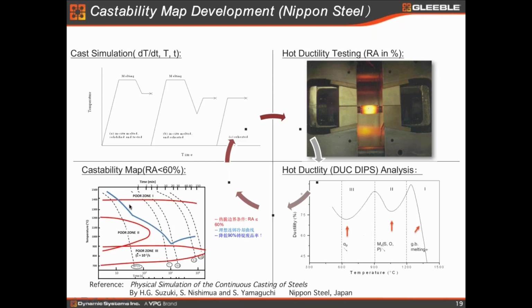So in this castability map you will see temperature versus time. They plot these three low ductility regions as contours in this map. We call it a castability map. What they see is this: in their original casting, the cooling rate is about 20 C per second, as you can see here. And this castability path actually goes through all three low ductility regions. So no wonder their casting had so many cracks.